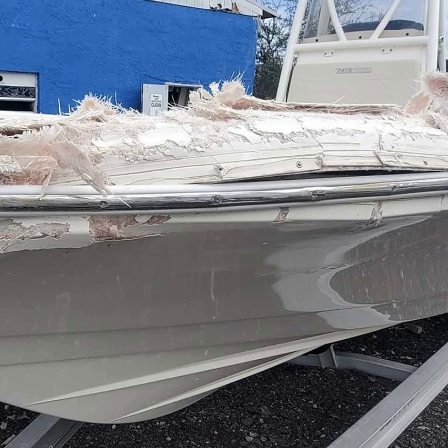And you have to use a little bit of common sense when you're trying to determine the difference between these two things, because when it comes to fiberglass repairs, there's just such a big variation on how acute the damage could be. If you're trying to repair some stress cracks, then you don't have to worry too much, because inevitably, in order to fix those stress cracks, you're going to grind the gel coat back to at least see the raw fiberglass underneath it. And then you'll be able to conduct an assessment at that point to see how much of the laminate needs to be ground out and replaced.